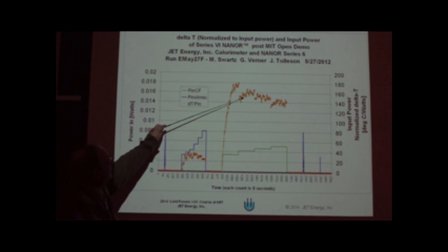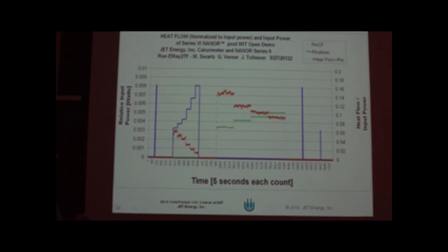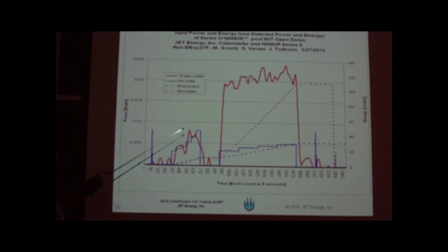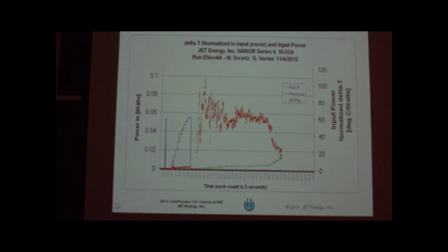And the reason we did this is in Natick is where we applied the magnetic fields, the high intensity. We did 1.5 Tesla, where we were flipping, we'll show you tomorrow, putting on 1.5 Tesla fields, flipping them every 10th of a millisecond, and putting on pulses that induce about 40,000 volts per meter across the device. That's how we make the M nanors. Anyway, here, before it becomes an M nanor, here's our energy gain. So we're still getting energy gain, and we see it for the heat flow, we see it for the calorimetry, nice energy gain. And here's in February, I think this is November, not February. November, we're still getting energy gain out.